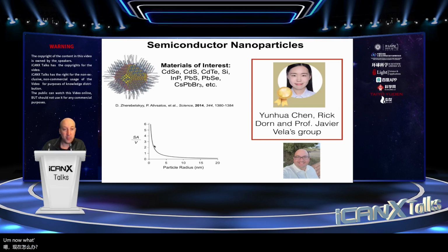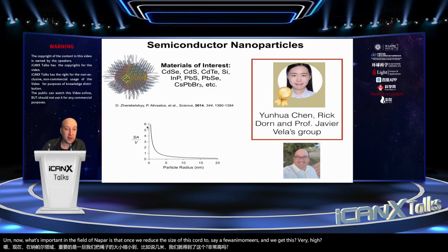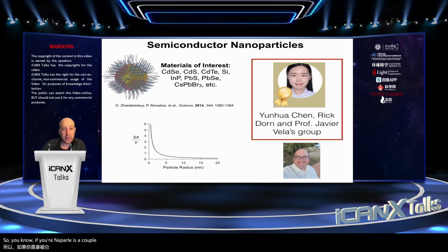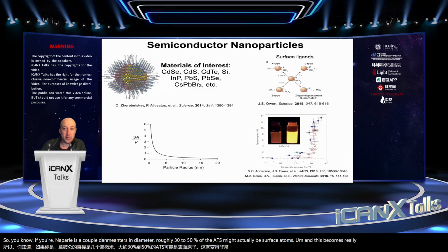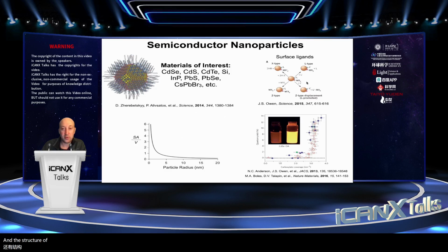Now, what's important in the field of nanoparticles is that once we reduce the size of this core to, say, a few nanometers, then we get this very high surface area to volume ratio. So, if your nanoparticle is a couple nanometers in diameter, roughly 30 to 50% of the atoms might actually be surface atoms. And this becomes really important to address because then the surface chemistry and the structure of those surface atoms can really dictate the bulk properties of the material.